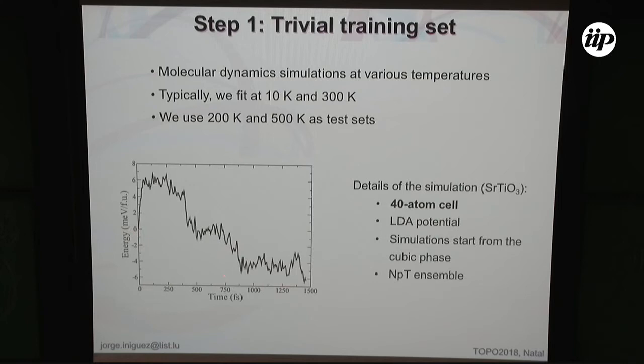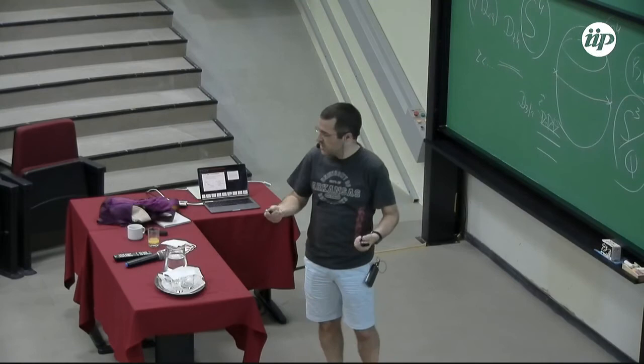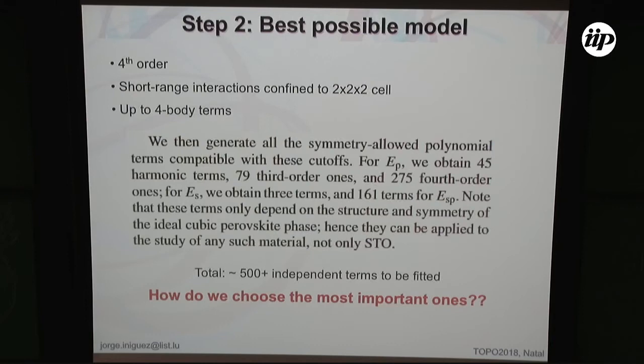The system starts cubic and over time the structural distortions in strontium titanate — rotations of oxygen octahedra — kick in and reduce the symmetry from the cubic phase. The crucial point is that I can run this simulation without knowing anything about the system. I start, I don't know what to do, I let go, and the forces take the system from the high-symmetry phase to the low-symmetry phase by themselves. Running at 10 kelvin, the system really goes to the low-symmetry phase.